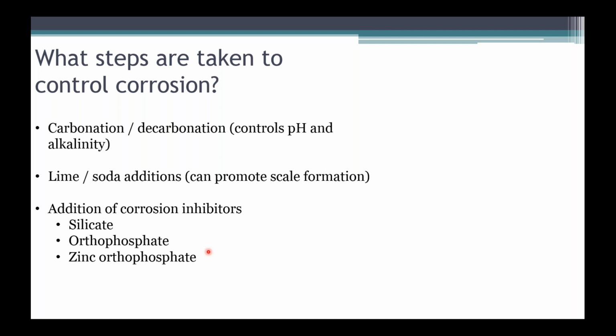So the steps to control corrosion are usually to try to keep many of the factors causing corrosion in a range that minimizes their corrosivity. Things like carbonation and decarbonation are used to control pH and alkalinity. Soda lime or caustic soda can be added to control pH, and in some cases to promote scale formation inside the pipes. And more recently, drinking water facilities have begun adding chemical corrosion inhibitors, things such as silicate and orthophosphate.